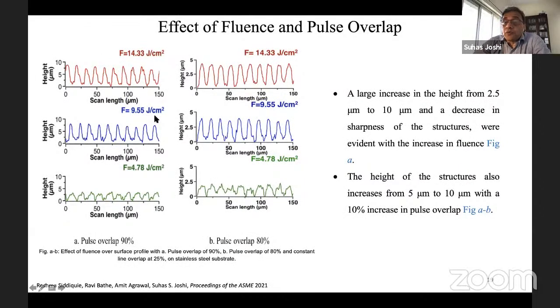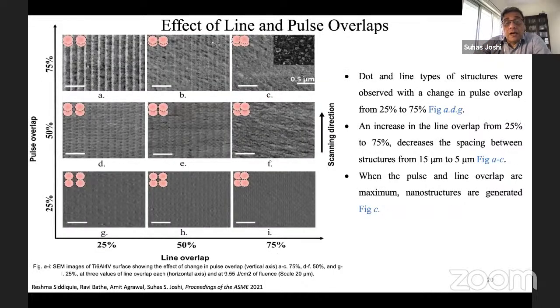Going into a little more detail on the profiles of the surfaces generated. You can see that at higher fluence, very sharp and deep profiles are created on both the surfaces. Whereas when the fluence goes down, the energy density goes down, the sharpness of the generated surface is considerably reduced. So this variation is in the order of 5 to 10 micrometers. So this gives some kind of picture of, on one side, the line overlap, and on the other side, the pulse overlap. The pulse overlap is along one line, and the line overlap is one line overlapping on the other line, something like side by side, and these pictures are here.